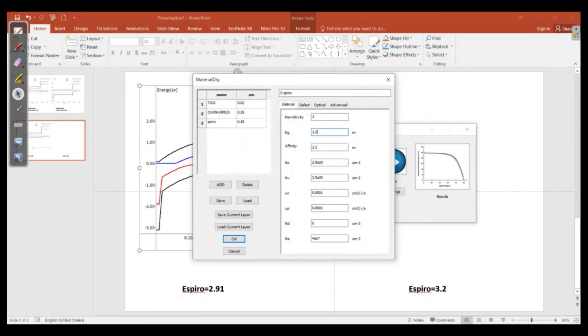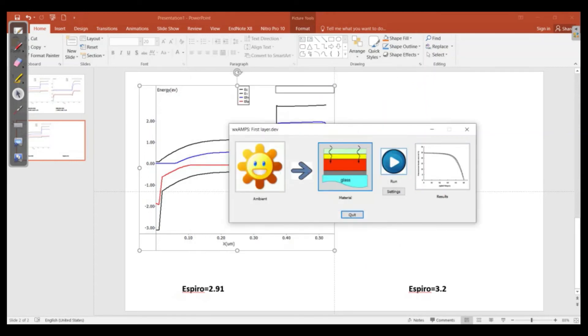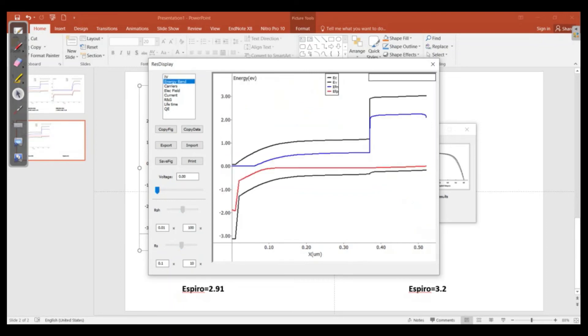Now we want to change the band gap to 3.2 electron volts. This will shift both the conduction band and valence band of the material. We run the simulation and observe that the energy level changes slightly and the efficiency decreases from 20.59% to 20.40%. A small spike begins to appear at the interface.